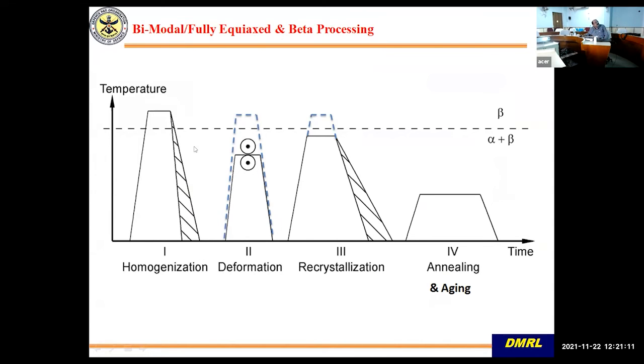The ingot, as I told you, is heated up high in the beta phase regime. So that is called homogenization. Then you can cool at different rates. Then deformation is first carried out in the beta and then in the alpha plus beta regime if you want a bimodal kind of structure. Otherwise, if you want a beta treated structure, you can just do deformation here and then annealing or recrystallization here, and you get a beta treated structure.